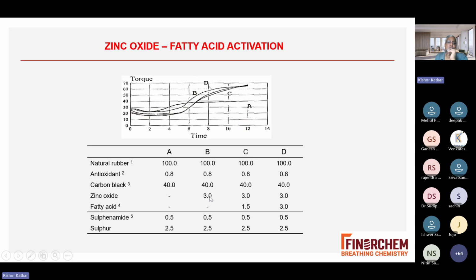Then in the second case, he has used zinc oxide but forgotten fatty acid, that is stearic acid. It is slightly better. It is like this, the modulus takes more time. In compound C, it has used stearic acid, but on the lower side, not sufficient. So you get it like this. In the final compound, which has optimum zinc oxide 3 phr and fatty acid, stearic acid 3 phr, you get a proper cure, good scorch safety, good cure rate, and good modulus. So what you understand is, when you are talking about sulfur and accelerator cure, you require activation with zinc oxide and fatty acid at a proper dosage.